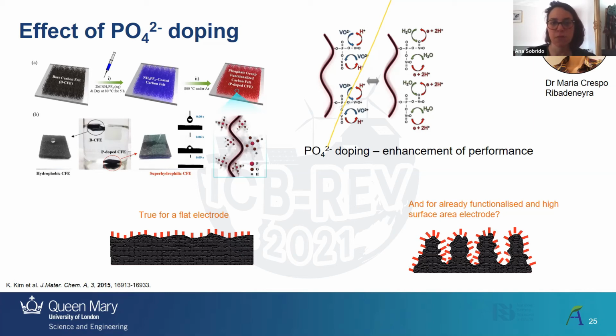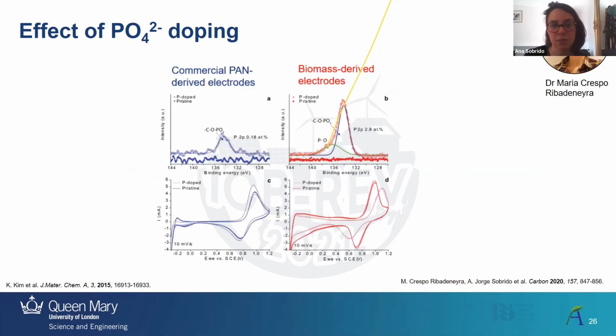So this seems to be true for a flatter electrode with a smaller amount of oxygen functional groups to start with. But what happens with a surface like ours, when we have a lot of different geometries with less flat structures, and which is already highly functionalized? In our case, surprisingly, we found a negative effect from the addition of phosphate, which I think was quite interesting, because it says that something different happens when you already have your surface really functionalized.